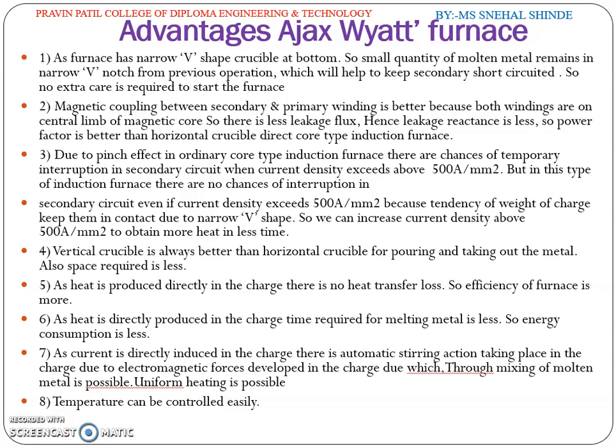Due to pinch effect in ordinary core type induction furnace, there are chances of temporary interruption in the secondary circuit when current density exceeds above 500 ampere per millimeter square. But in this type of induction furnace, there are no chances of interruption in the secondary circuit even if current exceeds 500 ampere per millimeter square, because the weight of charge keeps contact due to narrow V-shape. So we can increase current density above 500 ampere per millimeter square to obtain more heat in less time.